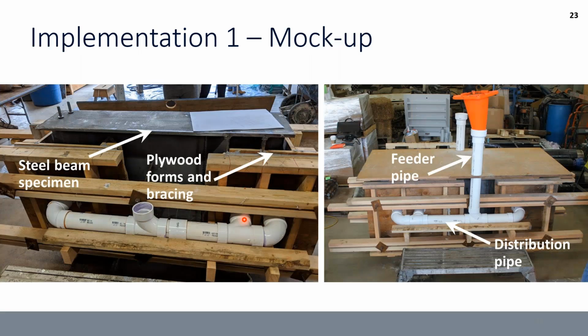So moving on to that mock-up, this is done in the contractor's yard, and this was their first example of trying what they had proposed for the formwork and the distribution system of the UHPC. So here is our steel beam and specimen. They just used plywood forms and bracing, and a PVC distribution system was used to enable casting from the top of the deck and filling multiple beam ends at once.